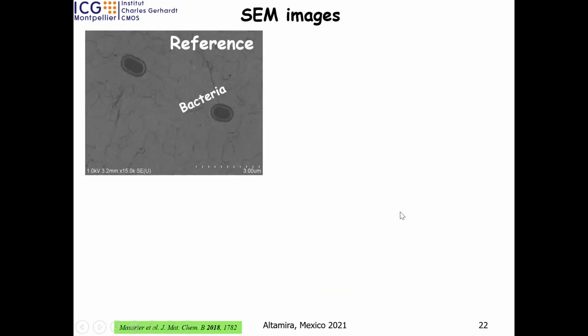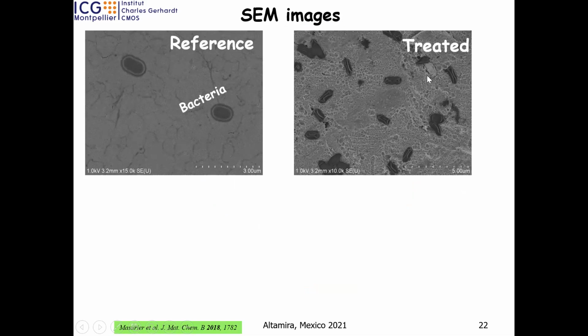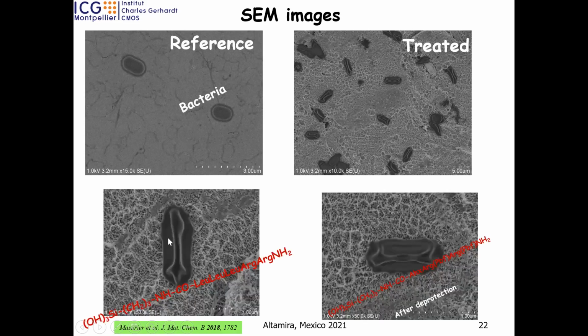What about antimicrobial property? The reference is a substrate without any coating, and you put the bacteria. As you can see clearly here, the bacteria grow very well on the surface. There is a lot of development on the surface. However, in the case where the surface was treated by dip coating with our colloidal solution, you can see clearly here the bacteria are not doing well. All bacteria are dead after 2 hours. In the other case, the bacteria stay for several days.